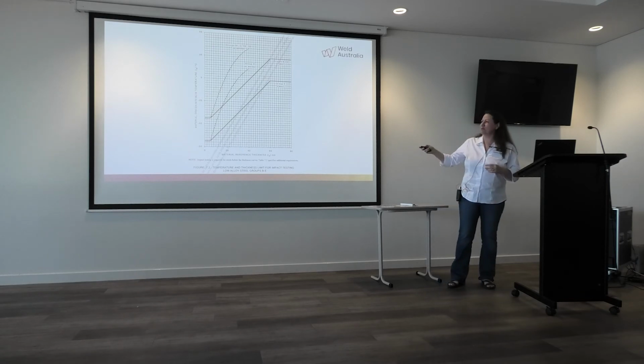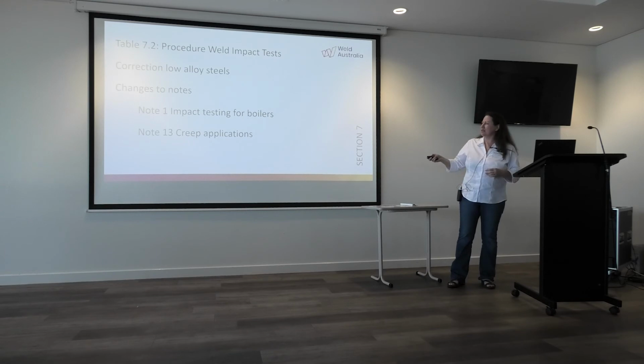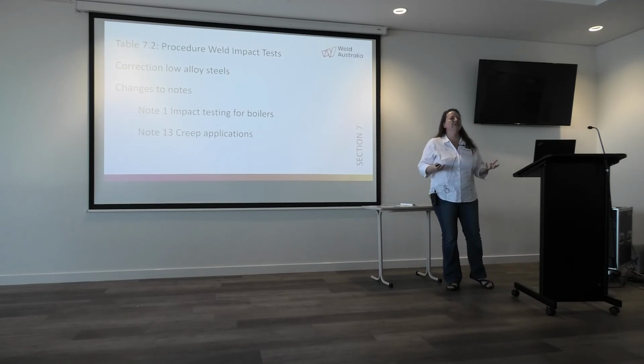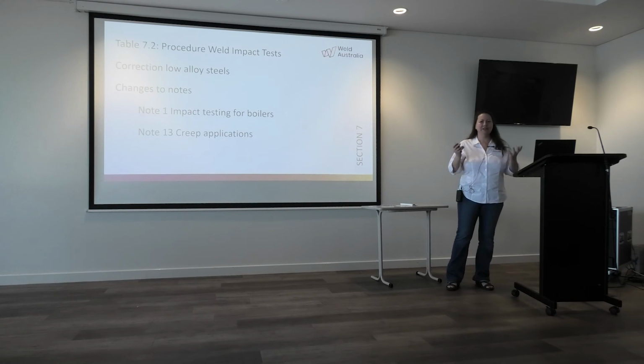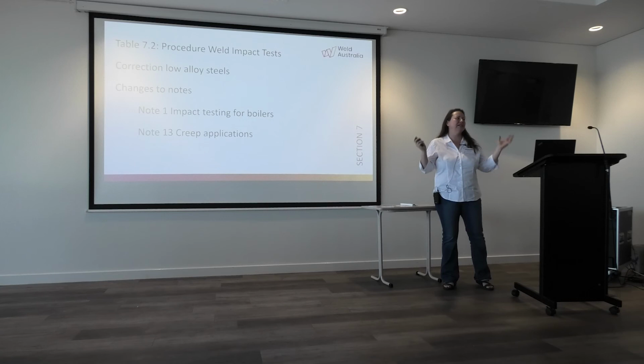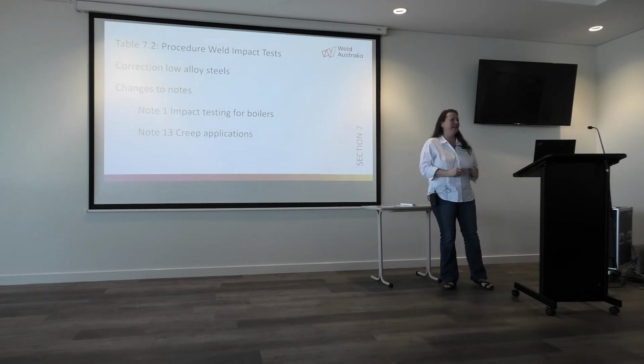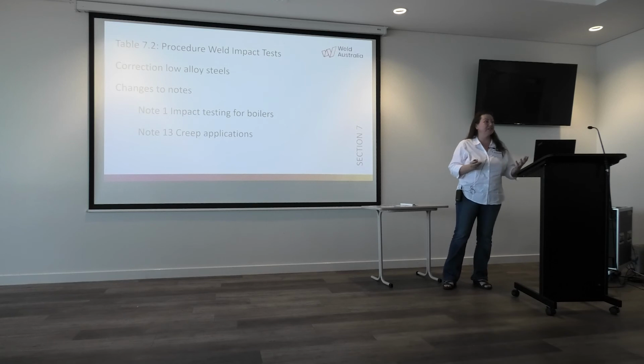So a bit of design aspects was added in the standard itself. And then also the notes were changed for the impact testing. Originally it said that for boilers, you don't have to do impact testing. And there seems to be this industry perspective that if something is operating at a high temperature, it's infinitely ductile and perfect toughness, and you never have to worry about it. But under creep applications, you actually lose your toughness.